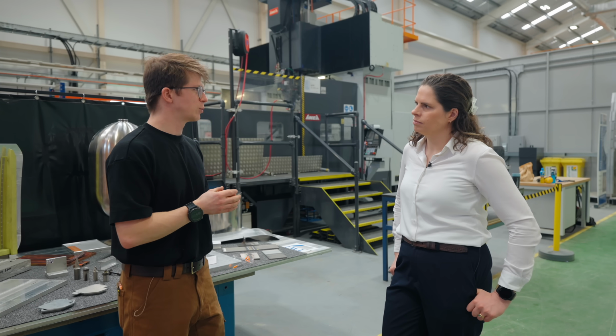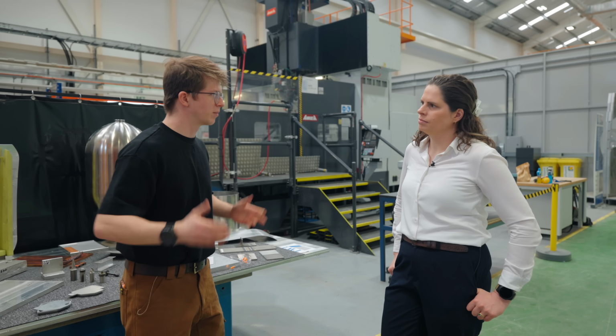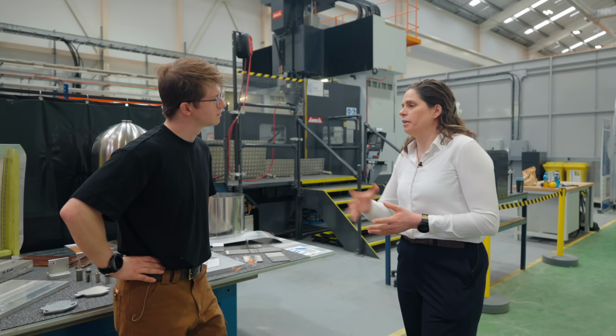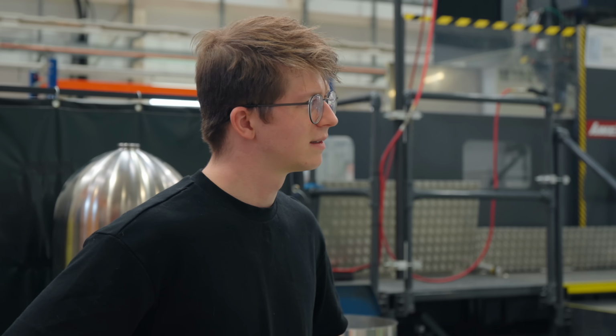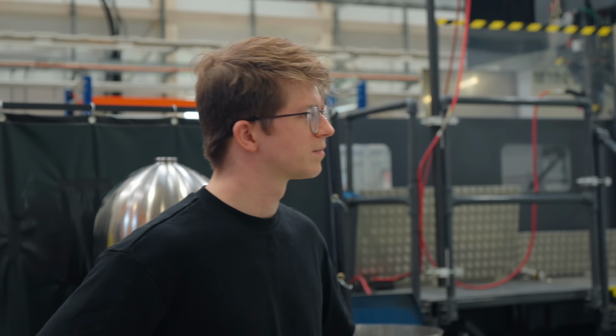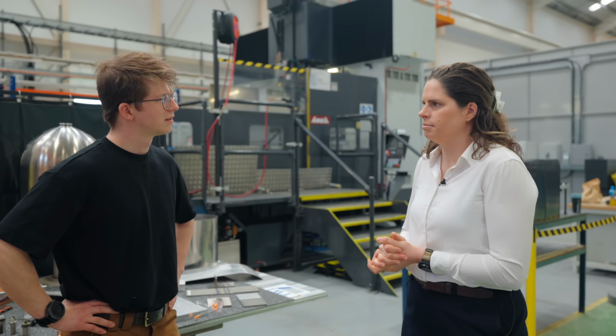So we're going to look at rotary friction welding. What would be the use case of rotary friction welding, and why wouldn't you just MIG weld the thing together? The use case of rotary friction welding, for instance, what I did my PhD on, aerospace discs. Within an aerospace engine, you're joining nickel superalloys. Those are really high temperature materials, and they're really physically hard. When you weld them, it's super challenging just to get a weld at a good enough quality to put into an aerospace engine. By rotary friction welding them, you get much better quality on the weld, and you're able to keep those properties really high.